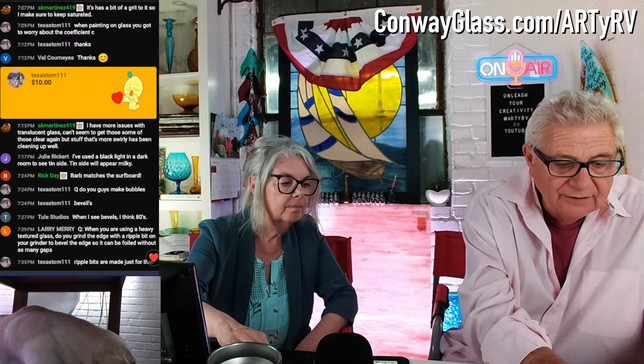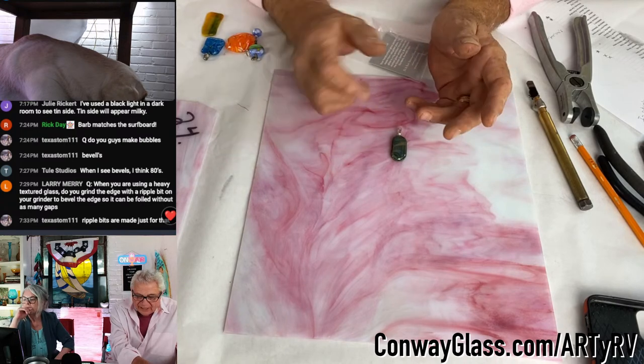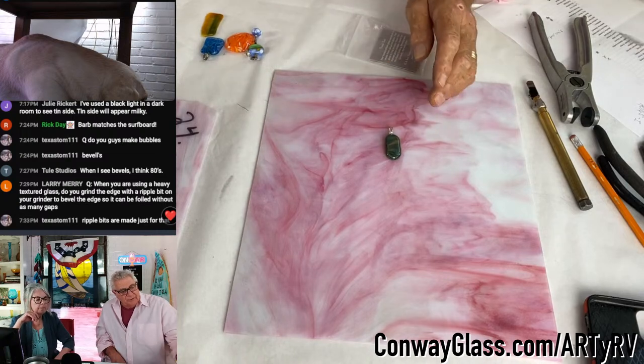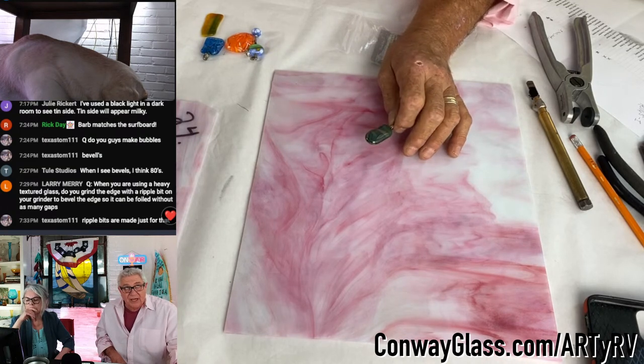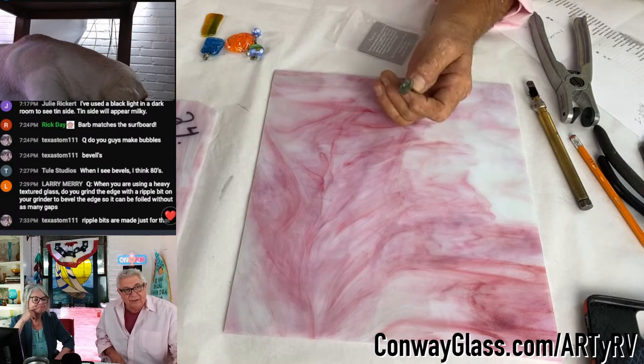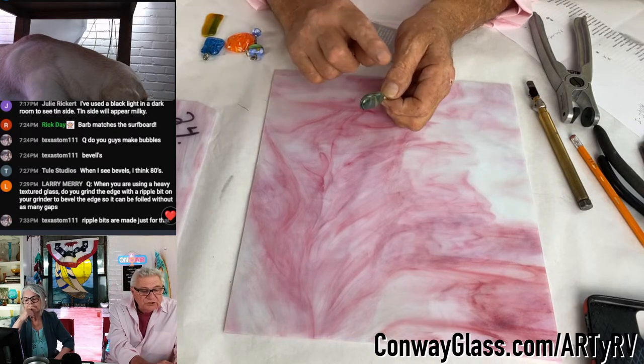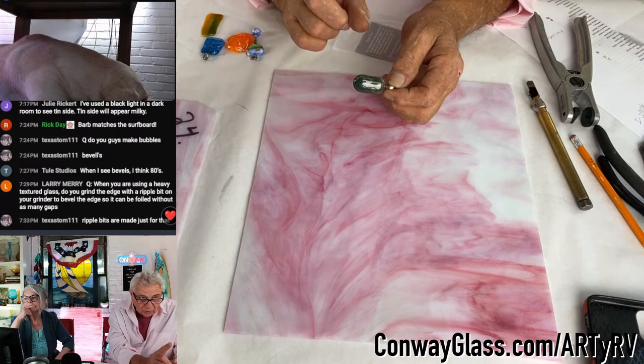The best thing I found is that textured glasses make really pretty pendants. Just one single piece of textured glass, cut into a shape, and then you fire it in your kiln. If you're using Bullseye or Uroboros, you don't need to spray devitrification spray, or what's called spray A, on it, because you're taking these pendants up to about 1350 degrees. You want to roll the edges so they're not sharp and they're polished.